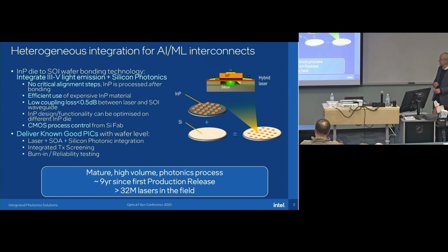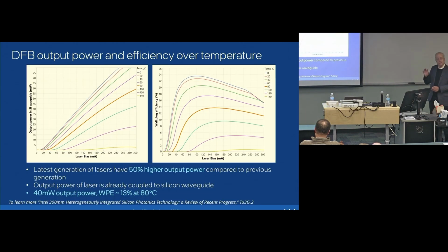They've now got 32 million lasers in the field, and these are good lasers. These things lase up to 140 degrees C, which is beyond what you'd expect, partially because silicon's a very good thermal conductor - better than indium phosphide. And good wall plug efficiency, 24-25%, which is important to get the power down to where you need it to be.